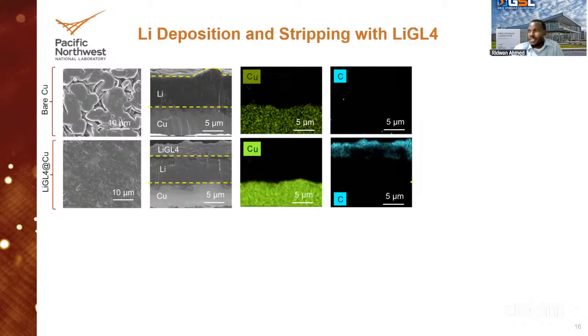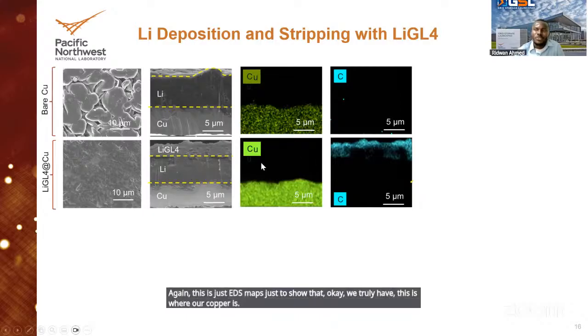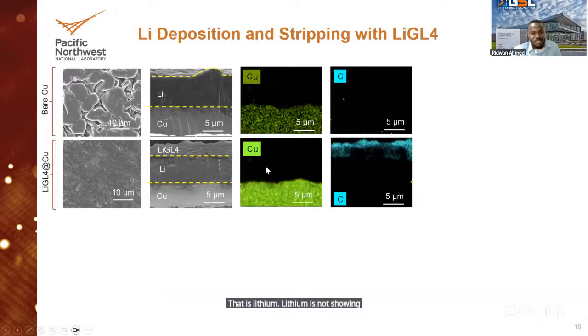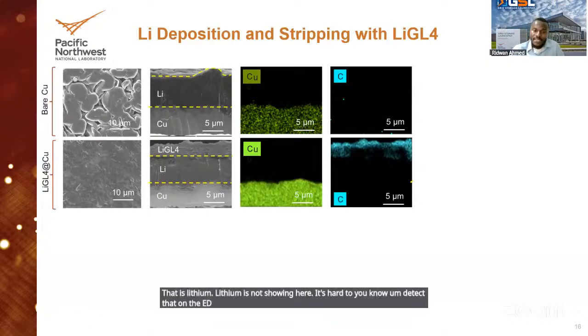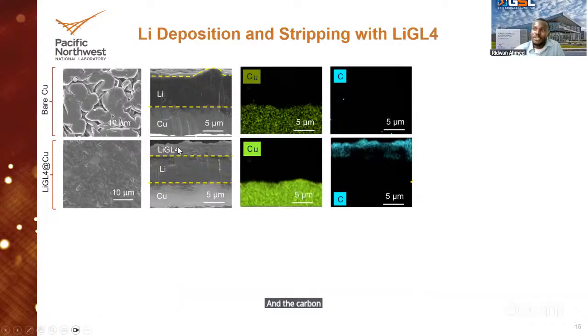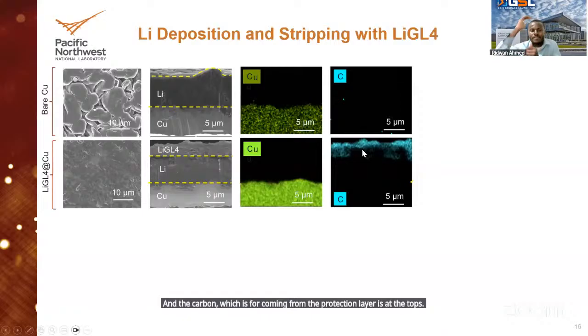Again, this is just EDS maps, just to show that we truly have, this is where our copper is. This is our lithium. Lithium is not showing here. It's hard to detect under EDS because it's a very light element. So that's why you see a dark region here. And the carbon, which is coming from the protection layer, is at the top. So that confirms that we have that coating layer on top of the lithium.